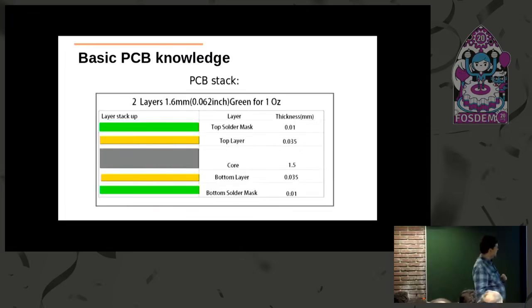The PCB stack is how the PCB is made with the different layers. You have a core, which is made of fiberglass with resin. Then you have 2 layers of copper. And then you have solder mask, which is 10 microns, and the copper is usually 35 microns. Total thickness is about 1.6 millimeters.